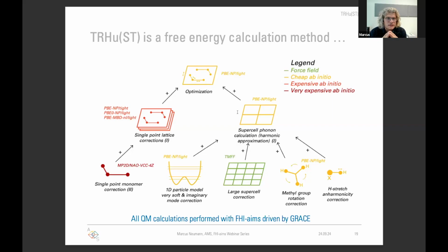And so for these ab initio supercell calculations, we do various corrections. If we have imaginary modes, then we explicitly sample the one-dimensional potential, and then we solve the one-dimensional Schrödinger equation to at least get some sort of correction for the anharmonicity of those modes. To get the phonon dispersion right, we do a very large cell phonon dispersion correction at force field level, and then we also correct a couple of other things that have proven to be less important. One important point here, and I'll come back to FHI-aims, is that every QM calculation is actually carried out with FHI-aims, so GRACE has a driver for FHI-aims.